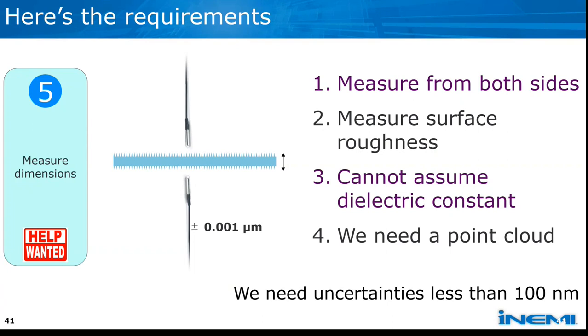The next problem is that your material might have surface roughness. So if the spot size of your dimensional metrology technique is large compared to the surface roughness, and the surface roughness is high, you might convolve that surface roughness into your thickness measurement, and that also might impact your permittivity extraction.